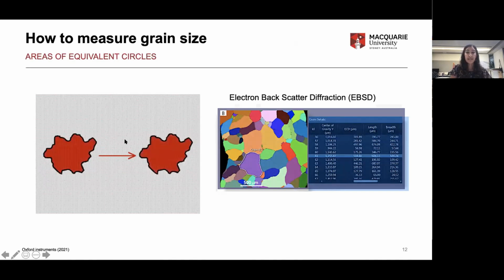This is a fantastic and really useful bit of information from electron backscatter diffraction, but this requires a huge amount of sample preparation. And often geological materials don't lend themselves well to silica colloidal polishing. And that's especially true when you have experimental samples, which by the time you've polished through, you're left with less than a millimeter of sample. So if the polishing goes wrong, then you're in big trouble. Electron backscatter diffraction also takes anywhere between 2 and 8 hours to just index 250 grains. So if time is of the essence and high throughput is the value of your work, then this probably isn't going to be the way that you want to analyze your grains.